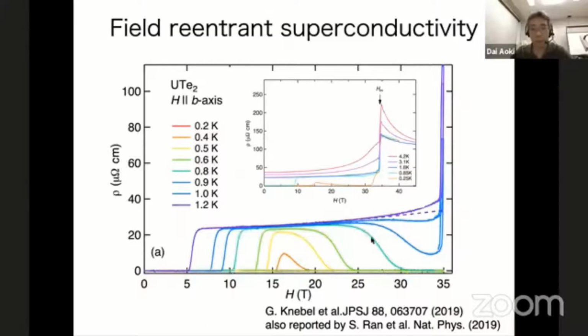Then again, it shows superconductivity here. So at high field, it really shows a reentrant superconductivity. And then at 35 Tesla, this jump shows the metamagnetic transition. And here is the measurement up to 50 Tesla.